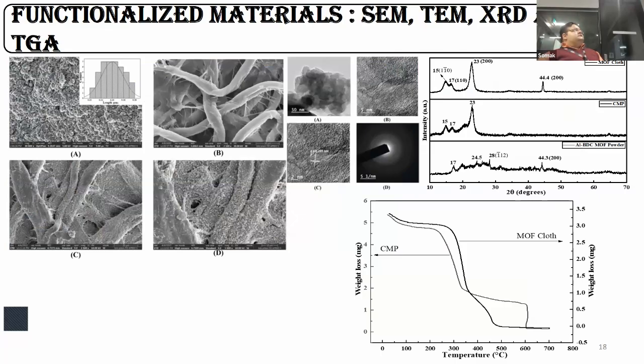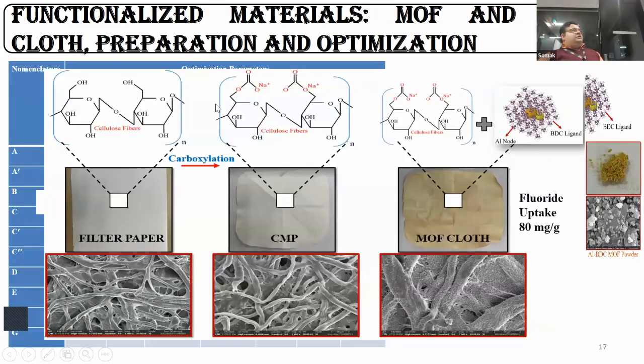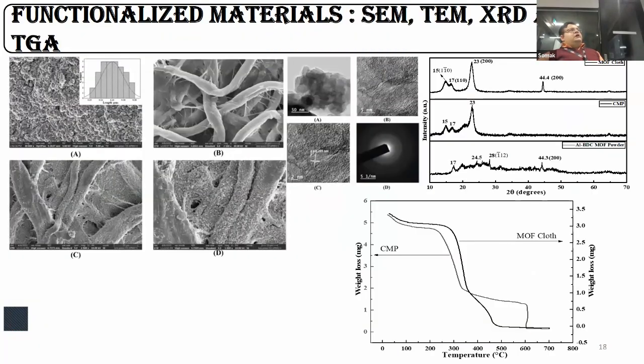As you can see, the MOF that we made had a size distribution in the range of 0.1 micron. This one was the filter paper that we had, and this is the carboxylated filter paper, the CMP as we call it, containing the anchorage sites. The anchorage sites get tightened, and once they're tightened, we can actually deposit the MOF onto the surface.